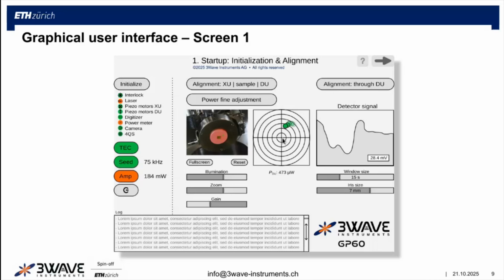Next step, when you hit the entrance of your detection unit with the laser, is that you click on alignment through the detection unit, and here our detector will show the intensity of the green light, strongly suppressed, of course, otherwise we would destroy the detector. Here you can see the intensity read by the detector. You can play with the window size to tune it. And now the idea would be that you play with the tilt and the tip in order to make sure that the light passes nicely through the whole optical setup. Finally, you can choose an iris size as small as possible that you don't lose any intensity from the detector, and then you are ready to go for the final measurement.